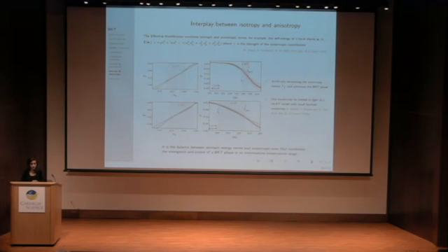Also, our results seem to be consistent with a model that perturbs the 2D XY model by adding a fourfold anisotropy field, a symmetry-breaking field, which can be viewed as reminiscent of what's left of our cubic symmetry in 2D.